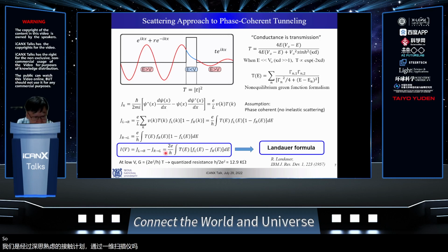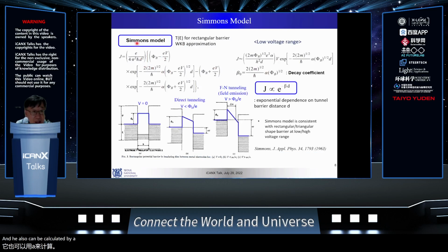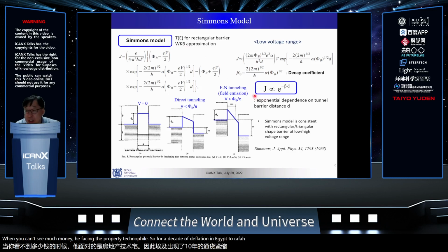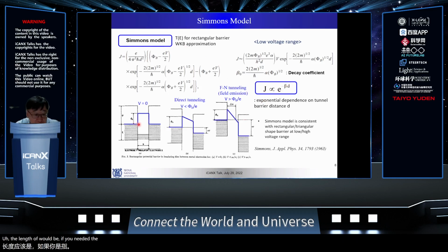Okay, so basically you can calculate the transmission probability T very carefully. For example, with electrons described as wave functions, we can calculate T like this, or people can use more quantum calculation methods. T can be calculated this way, with a coupling. T can also be calculated by the Simmons model. In that case, the transmission probability T is calculated by the so-called WKB approximation, and it gives the famous result that the current density depends exponentially on the length D, the molecular length. Current or resistance depends exponentially on D with some coefficient beta.